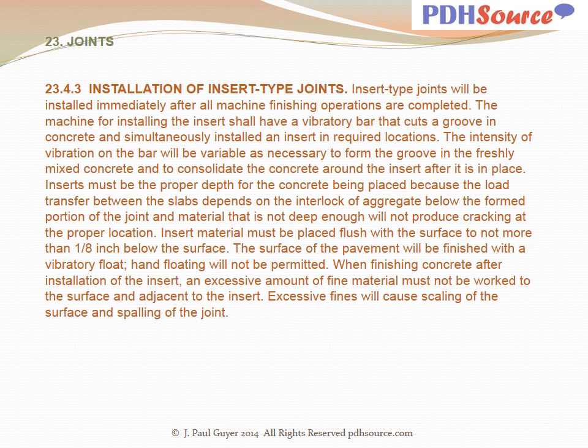When finishing concrete after installation of the insert, an excessive amount of fine material must not be worked to the surface and adjacent to the insert. Excessive fines will cause scaling of the surface and spalling of the joint.